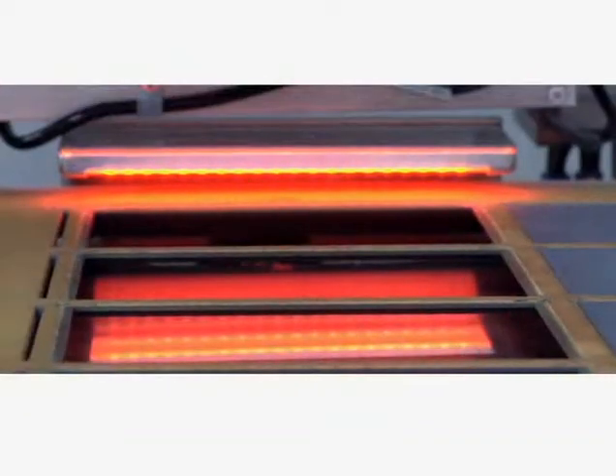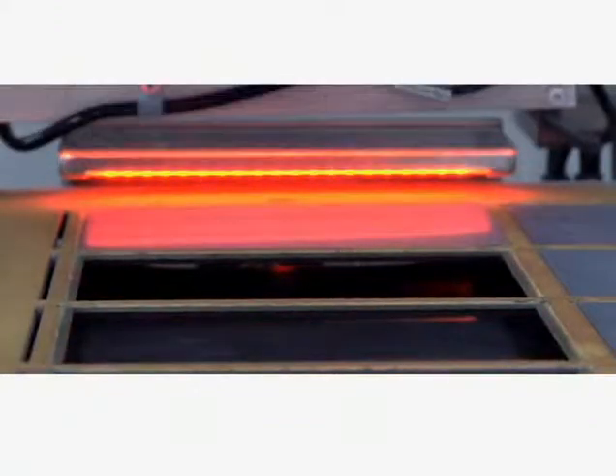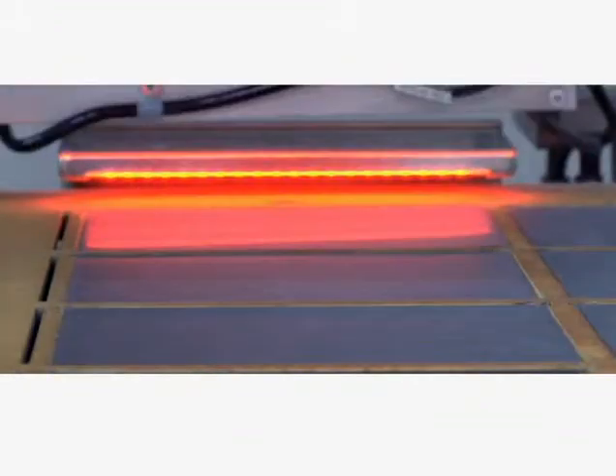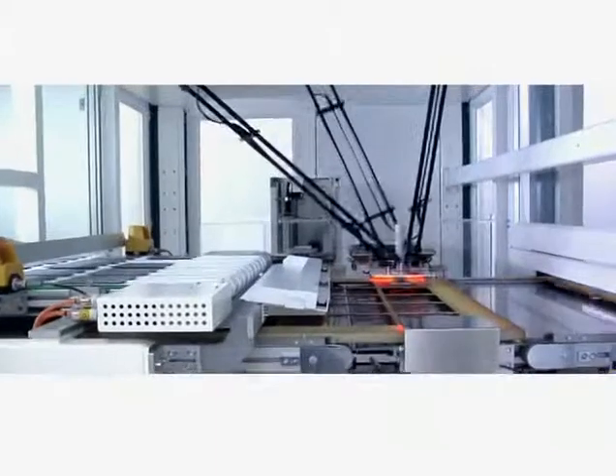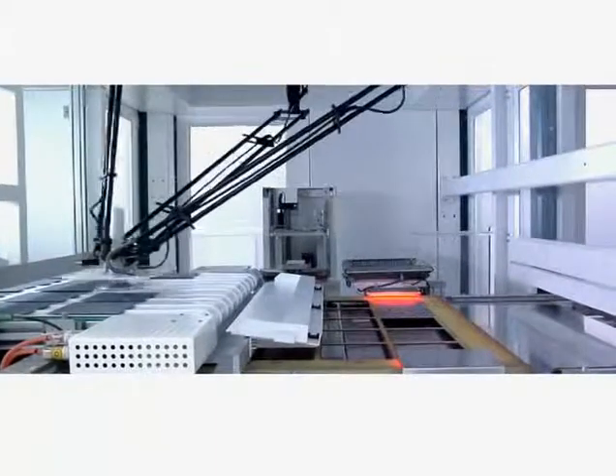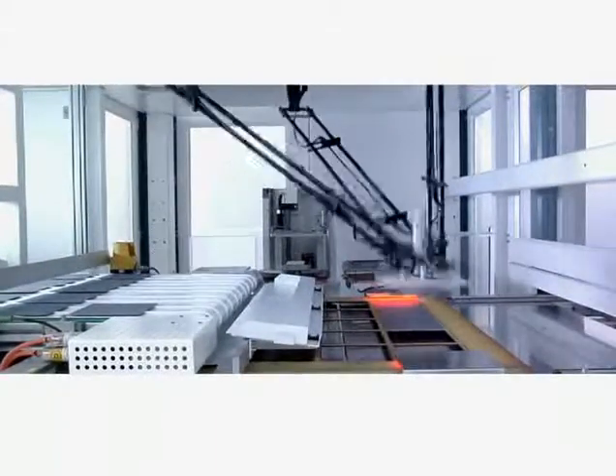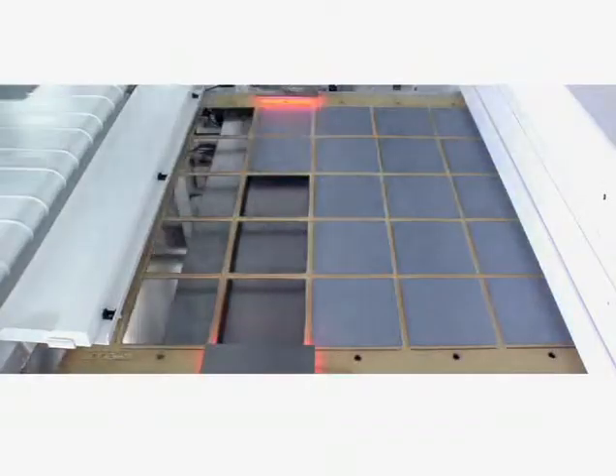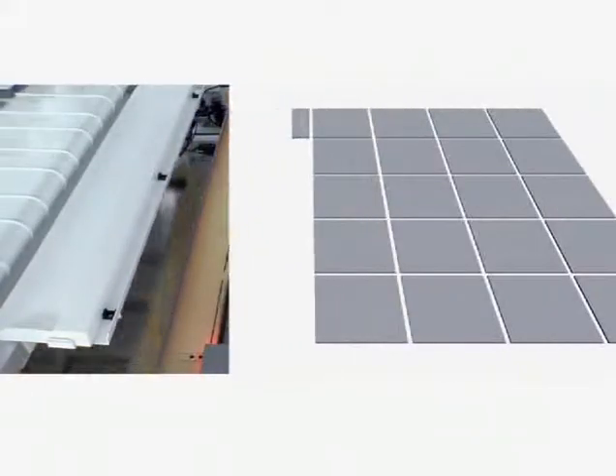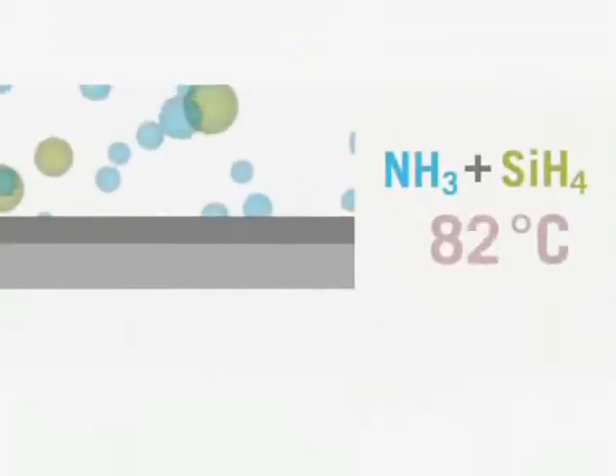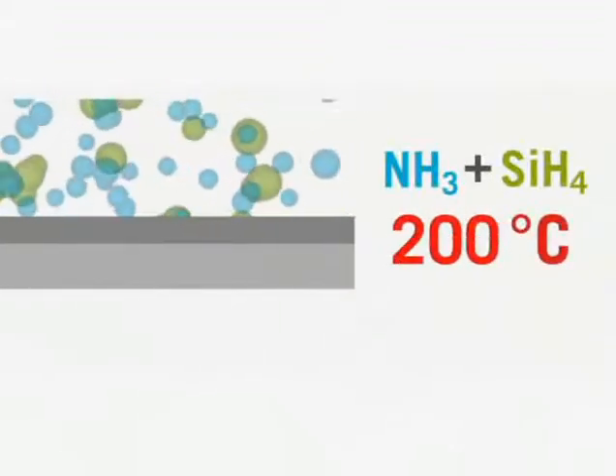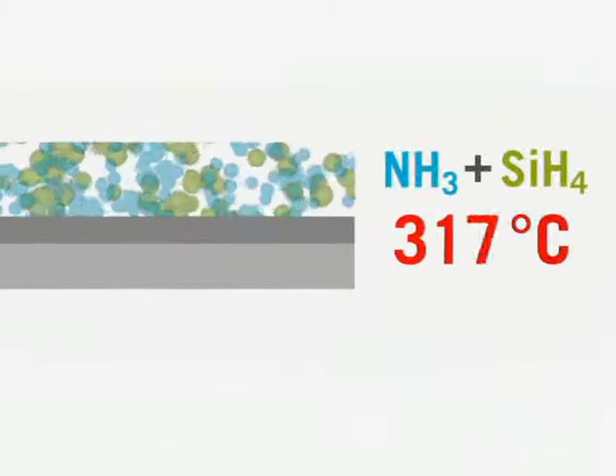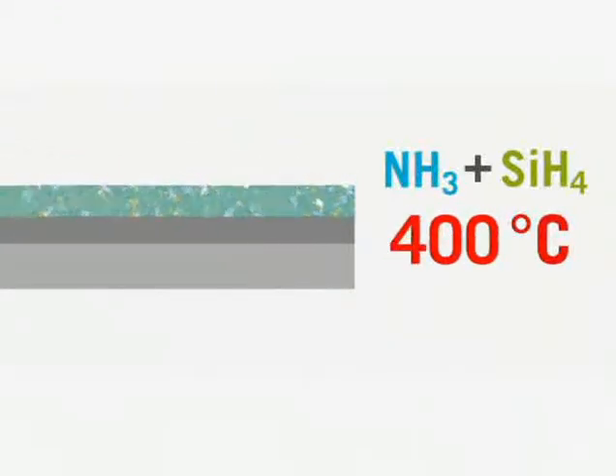To ensure that as little solar radiation as possible goes missing, a layer of silicon nitride is attached to the cell. This gives the cell its typical blue color. Before being coated, the cells are transferred into Sigrabond trays. In a plasma-reinforced vacuum process, the reaction gases ammonia and silane are deposited onto the surface of the wafer in the form of silicon nitride.